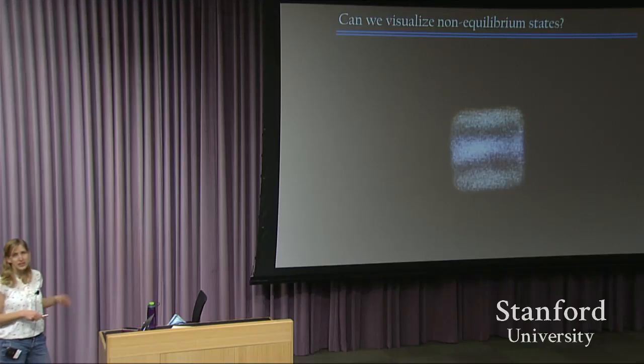Okay, so all of that was in thermodynamic equilibrium. I told you that we had this hypothesis for why, say, smaller particles were loading at lower hydrogen pressures. So we wanted to know, can we visualize non-equilibrium states? And here's one video, ironically captured on an iPhone 6, where different colored regions of the nanoparticle correspond to different phases.